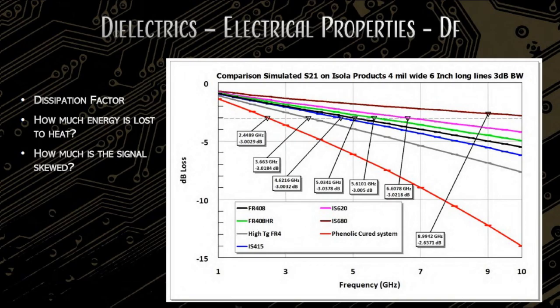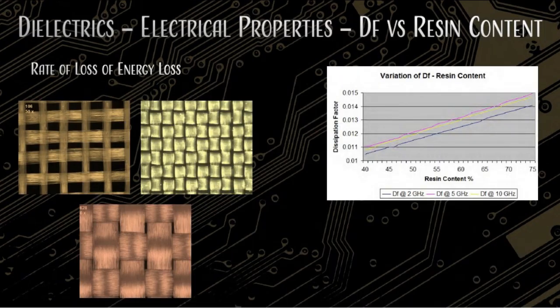All right, so as we were mentioning a second ago, it's different numbers. If you're using a very open weave, as your signal propagates in the electric fields that follow a trace, the area in between is going to be full of epoxy resin, where the dielectric constant is lower, and then as it travels and it hits the fiberglass, it's going to be higher, lower, higher, lower, higher, lower, higher. Every time that it changes, a little bit of your signal is going to be reflected back, a little bit of it's going to be absorbed, most of it's going to transmit.